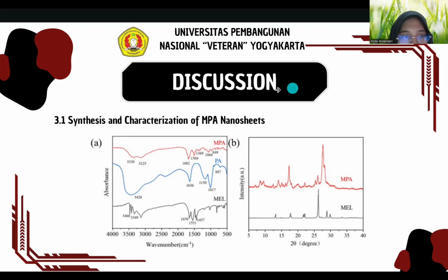FTIR spectra, figure 2A, showed the characteristic amino peaks at 3,468 and 3,349 centimeter observed in melamine but separate in MPA, with new peaks at 3,330 and 3,125 centimeter attributed to NH3+ and slightly unsaturated amino.